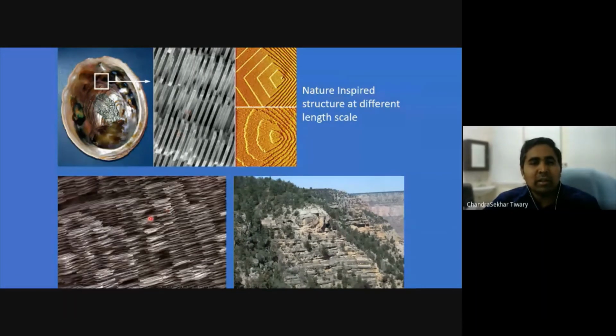And there was work already at microscopic level. When I say microscopic, what I mean is they took the sea shell, or a nacre-like structure. There is a lot of work here, and they break them. And what they see is nice plates of ceramic separated by organic layers. Just because of this kind of architecture, you get a much higher combination of strength and toughness. But these are at nanoscopic or microscopic level. You can see this length is 20 micron, and each of these plates is around a couple of microns or half a micron.